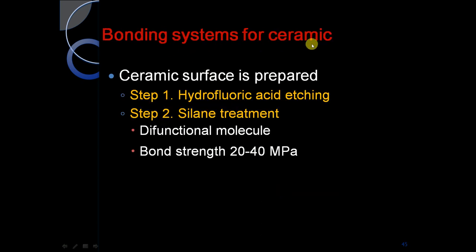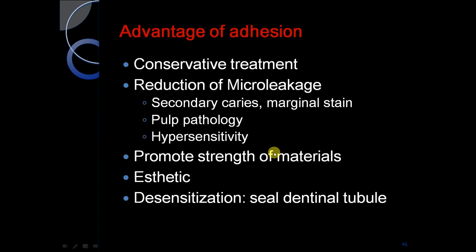Bonding system for ceramics: the ceramic surface is prepared. Step 1 is etching with 9.6% hydrofluoric acid (HF). Step 2 is silane coupling — a difunctional molecule is used. Bond strength is 20 to 40 MPa.